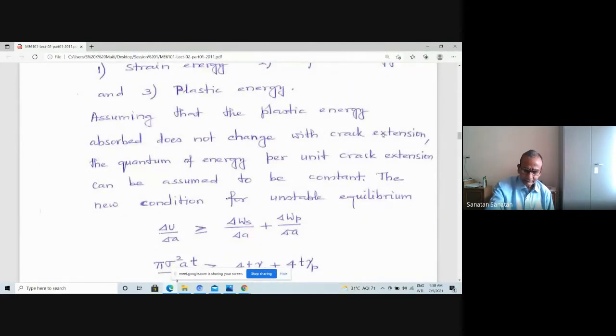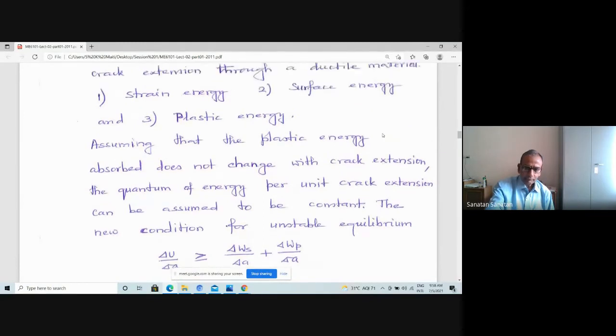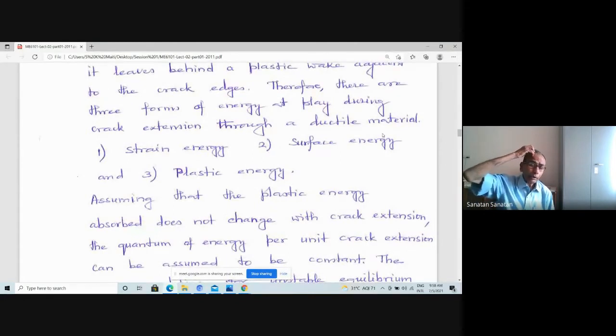Irwin and Orowan stated that, again we go back to the model that was considered about the material failure. When you are trying to talk about a material with a crack or a structure with a crack, as you load it, in general stresses and strains are very high near the crack tip, where stress concentration prevails, and therefore the material, rather than just failing, will give rise to, first of all, plastic deformation. So plastic deformation will take place, and then probably the crack will propagate. Before the crack propagation, you have deformation energy or strain energy in the body. Then if you create a new surface, surface energy is also there. But before it becomes actually a surface, that material will deform plastically.